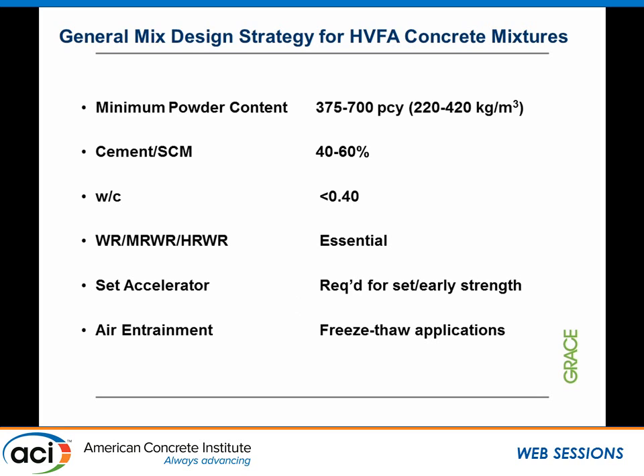Okay, for us in here, and I'm talking about this high volume fly ash mix, we are talking about a content of about 375 to 700 pounds per cubic yard in the 40 to 60% range. So I'm really moving up in the cement SCM content. Water cement ratio typically less than 0.4. And in this case, chemical admixtures, particularly dispersing agents, are critical. Set accelerator, because of the set time problem, is also important. And a lot of times in North America, with freeze-thaw issues, air entrainment is an issue.